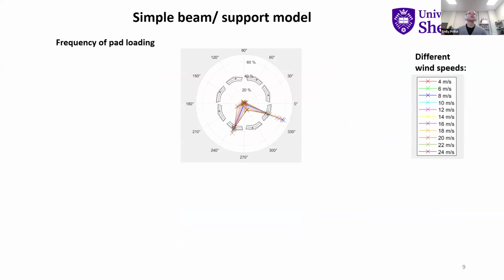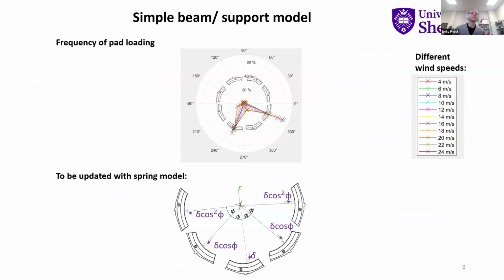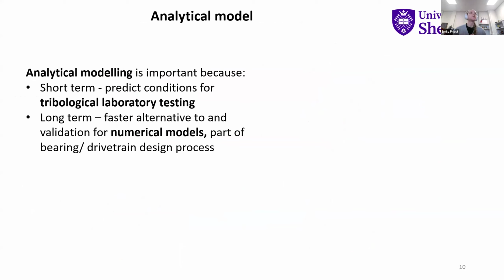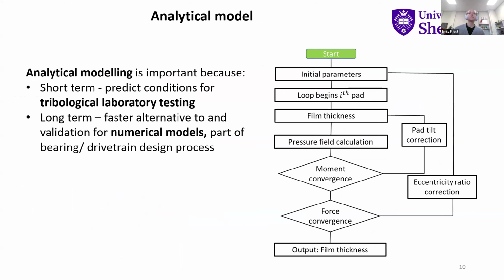So we also found the frequency of the pad loading. We found that 2 pads were definitely more loaded than the others, and just to say that in the future we're going to update this with a spring model. So looking at the analytical model, we built an analytical model, which is important so we can do our tribological lab testing, and that's just a little schematic of what we did.